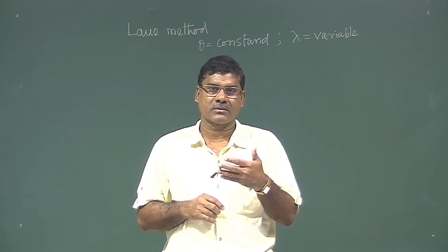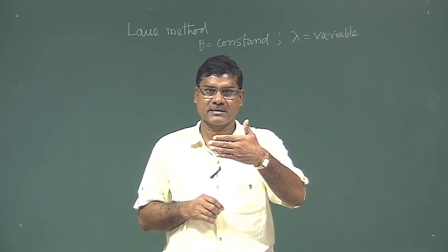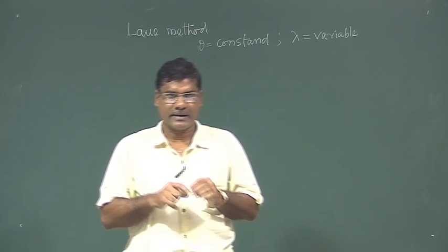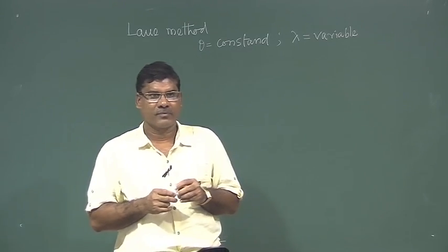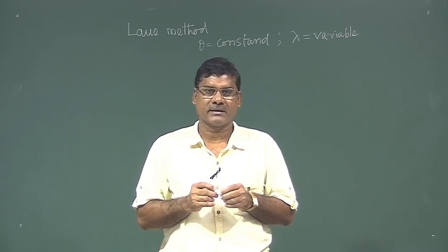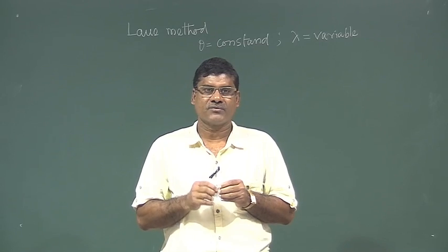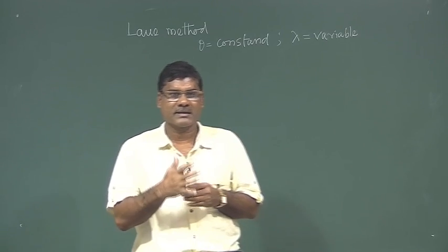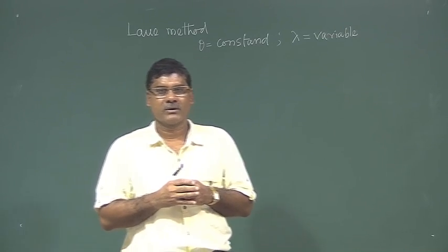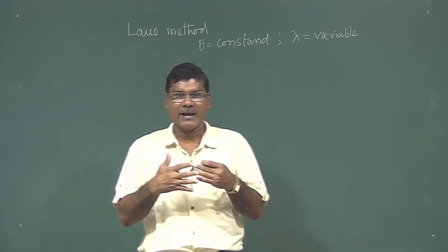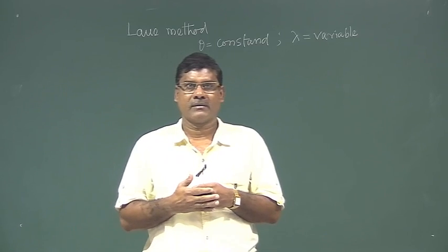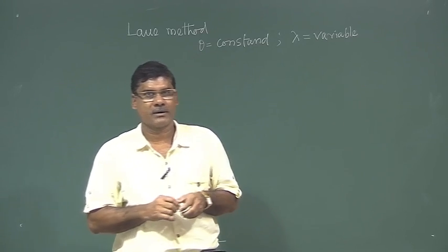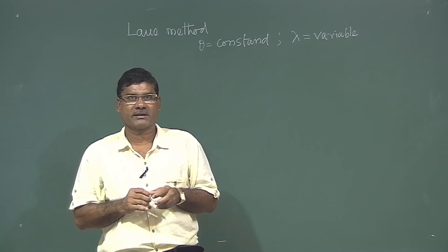So, the Laue spots on an X-ray plate or on a screen are arranged orderly, basically following the crystal symmetry, and each point is a plane. So, in a real crystal, whatever planes are there, they are oriented in different directions. That can be represented with points on a plane. This has some particular advantage that we will discuss later on.